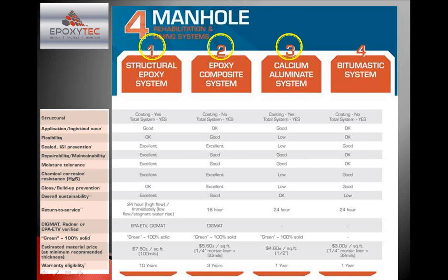Chemical corrosion resistance, again, slightly better than Portland cement, but still porous. The porosity results in bacterial buildup, which causes the breakdown from the hydrogen sulfide. This is eligible for a 1-year warranty. Material price on application is at about a 1/2 inch build, which is what's recommended, is about $4.60 per square foot, or about $56 in material per vertical foot on a 4-foot manhole.